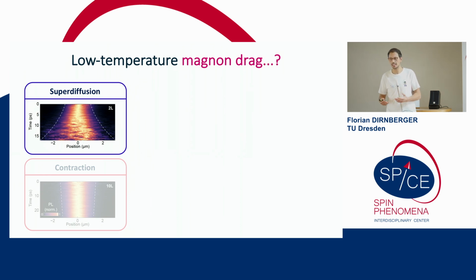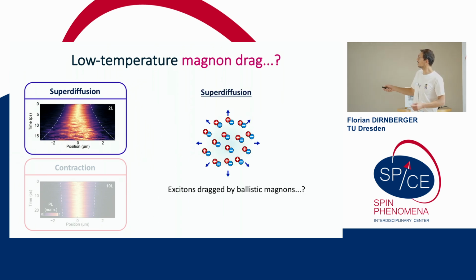Okay, so as I've mentioned, currently we don't really understand what's happening with these two phenomena. The only thing I can offer right now is to speculate how, in a magnon drag picture, we could maybe try to understand them. Regarding the superdiffusion of the excitons, one could, in principle, think about a process where the laser pulse creates a magnon wave, but the magnon wave now just propagates ballistically at low temperatures. It's like a coherent propagation, even on very fast timescales, and that just drags along the excitons. That would, in principle, account for how excitons can move basically ballistically through a crystal.